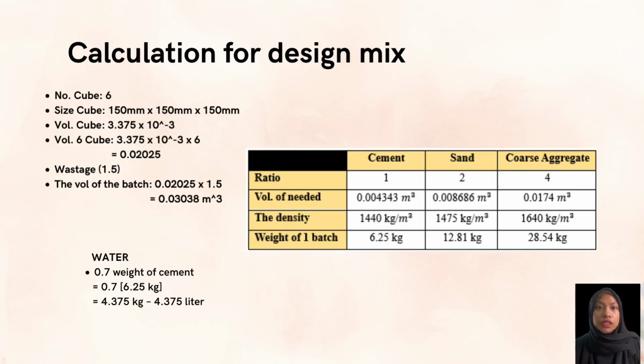So this is the calculation for the design mix. We use 6 cubes for one batch, where the size of the cube is 150 millimeter. For the cement, the design ratio is 1, and the weight of one batch is around 6.25 kg. For sand, we use a ratio of 2, and the weight of one batch is around 12.81 kg. For the coarse aggregate, we use a ratio of 4, which for one batch is around 28.54 kg. For the water, it is 0.7 of the weight of cement, which is around 4.375 kg or liters.